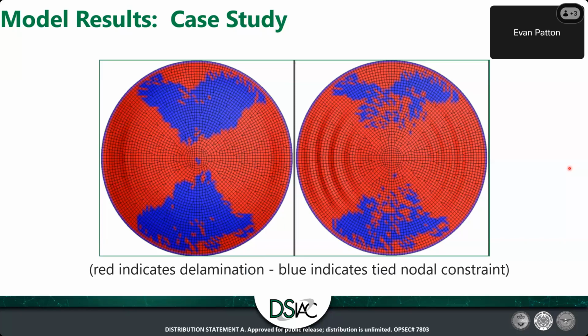Okay, gotcha. A question just came in on the simulation part. Does the correlated material card performance hold when you're applying it to a larger mesh size to be used in a full vehicle simulation? That's the tricky part, because if you're dealing with a larger element, that element's going to erode if it hits, quote unquote, failure. So obviously there's going to be some mesh sensitivity, especially when you're talking about damage and what kind of damage you're expecting. In this case, we didn't really know what we were expecting, but a 3 millimeter mesh size, we figured, would be very representative of a localized area of damage.